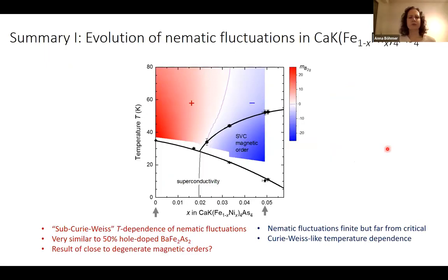So let me summarize my first part. Phase diagram of the 1144 and the B2G elastoresistance coefficient here. On the high nickel content side, the magnetic system, we do find finite nematic fluctuations, even though this is all tetragonal and the transition is also to a tetragonal magnetic state. And these fluctuations are far from critical. But they nevertheless have a Curie-Weiss-like temperature dependence. On the other hand, we find evidence for a, let's call it, sub-Curie-Weiss-like temperature dependence of the nematic fluctuations.